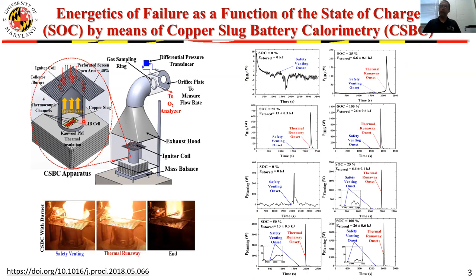So when we started playing with this device and performing these measurements, we quickly realized that that's not the only source of heat in the cell. During the thermal runaway, the cell ejects a considerable amount of materials, and it's usually a combination of gases, aerosols, and solid particulates. And early on, it was apparent that, based on the composition of the cell, some of this must be flammable. So we looked into understanding how much energy would be generated if these aerosols were to burn.